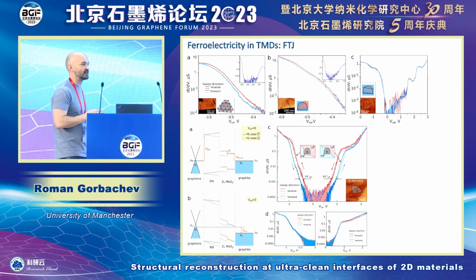Controlling this and making it wafer scale is a separate issue, and I'm not going to touch on that. But there is a lot of promise in this kind of devices, and keep in mind that these are very highly optically active systems. So all of this would change excitonic behavior. This switching is not just electric, it is also optical switching, because associated with ferroelectricity, you also have an exciton sitting there, which is polarized up or down because of the ferroelectricity. And so by switching these domains, you're also switching the energy of that exciton inside. And so I foresee in the future there will be a lot of interesting devices where people combine optical measurements and ferroelectricity and try to do this kind of hybrid functionality.